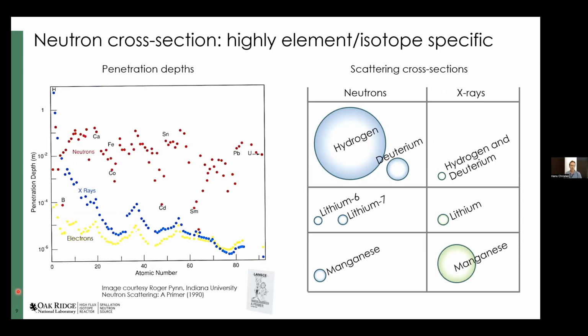So on the left, you have a chart that shows the penetration depth of neutrons, X-rays, and electrons into a material. This is a log scale. If you look at X-rays penetrating into the material, there is a more than 1 million change of how deep an X-ray goes into material, depending on whether it is lead or whether it is water. For neutrons, the scatter is all over the place.